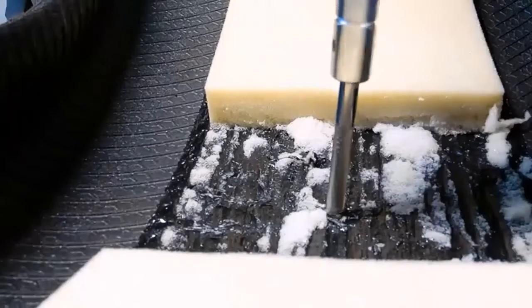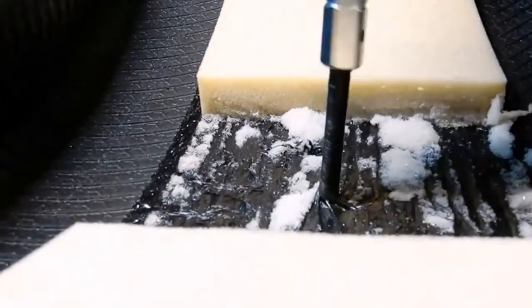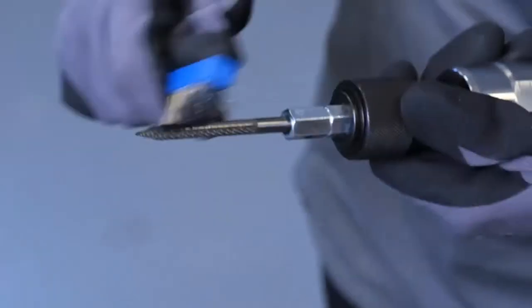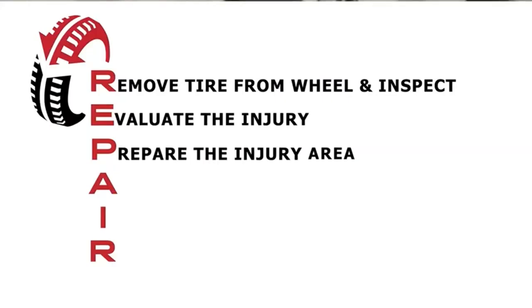Now drill out the injury from the inside of the tire and repeat this process a minimum of 3 times. Next, repeat this procedure 3 times from the outside of the tire to ensure proper injury preparation. After drilling the injury on a tire with a tacky adhesive, it may be necessary to clean the carbide cutter afterward. To do this, simply take a wire brush to remove any adhesive that may be stuck on the cutter. This concludes Tech Sound Suppression Tire Puncture Repair.